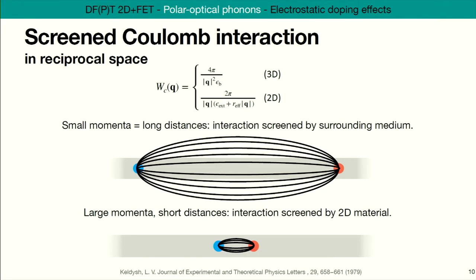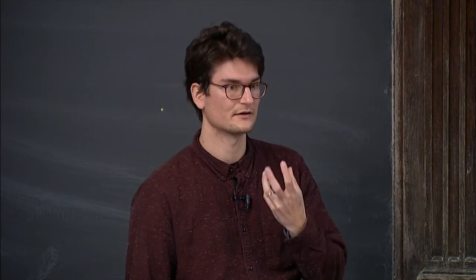Now if you go to large momenta, this term dominates, and we're looking at short distances in real space. Imagine the same charges but much closer. Depending on the thickness of the material, if you get them close enough, the field lines are going to stay within the thickness of the material, and in this case all the electric field is screened by the material itself. This term dominates, and this r_F here is really a material-specific parameter that comes from the screening of the material. This is just the first order of the dielectric function. In general, it's a bit more complicated, but this gives the main idea of what's happening.